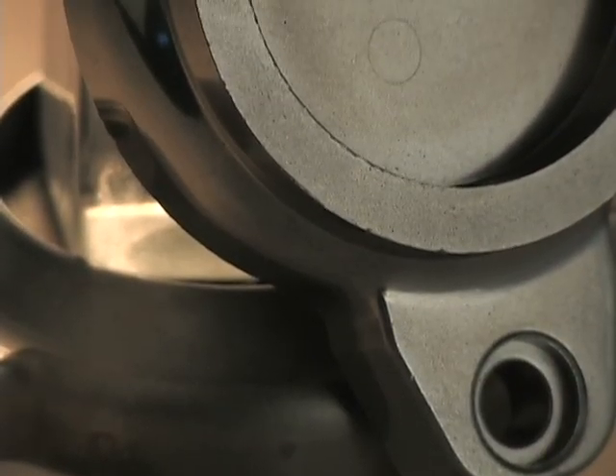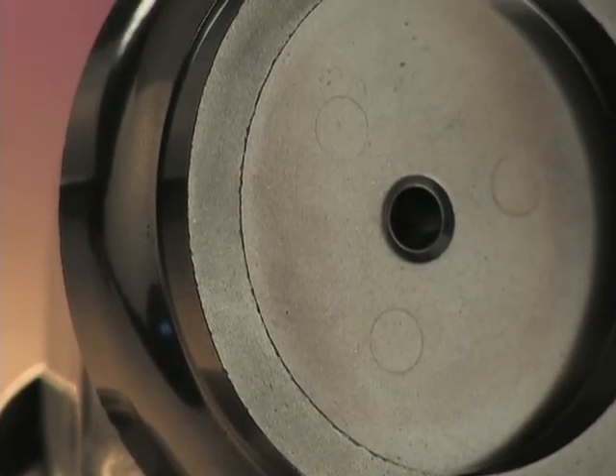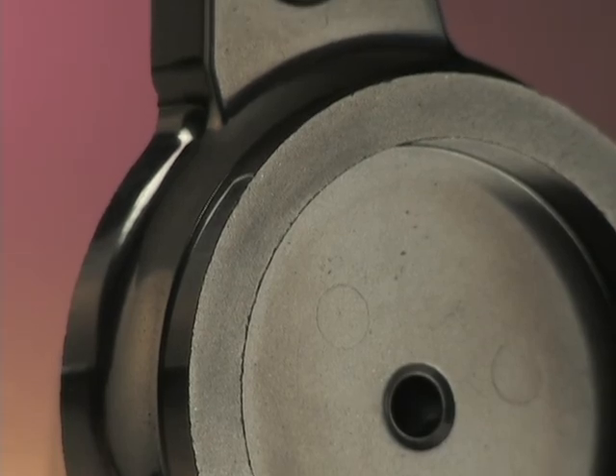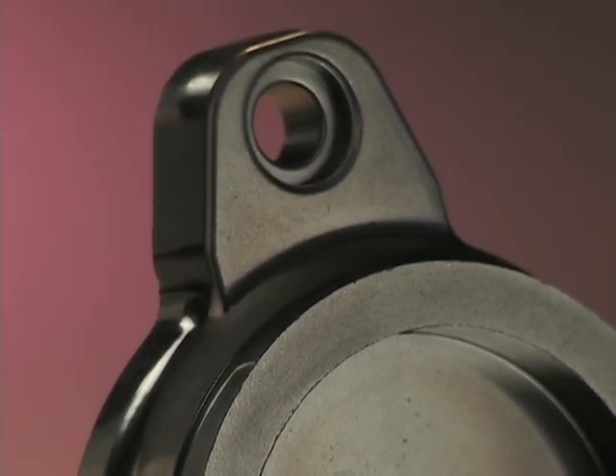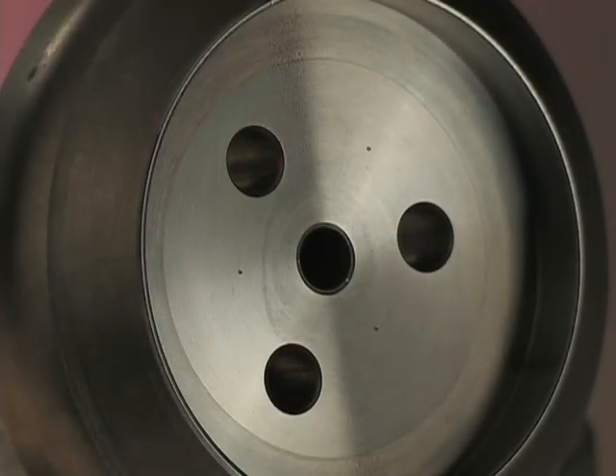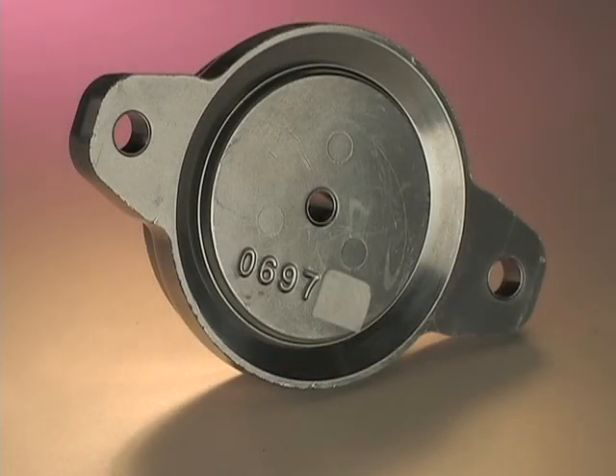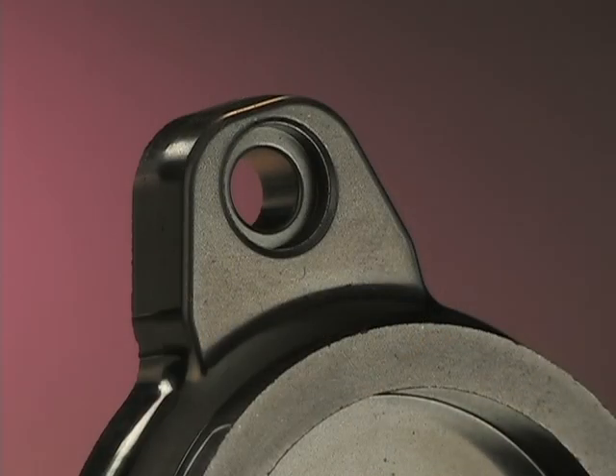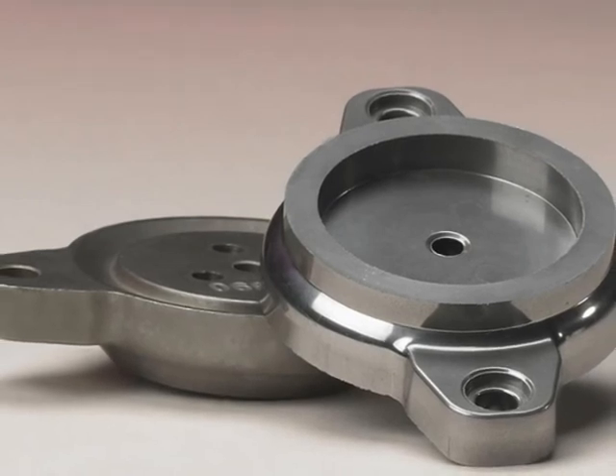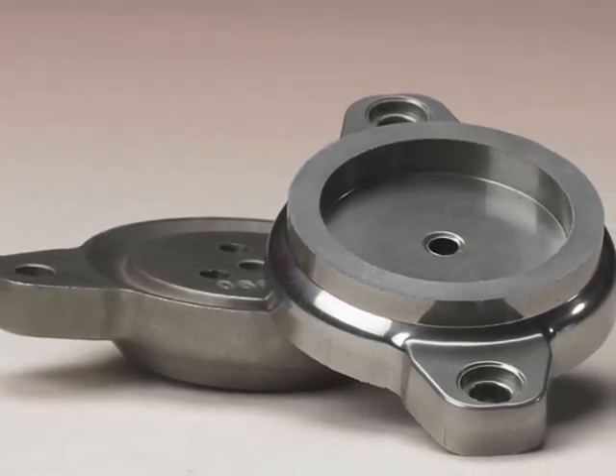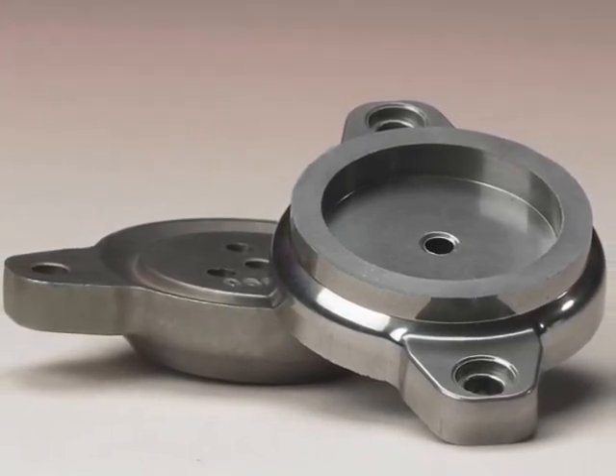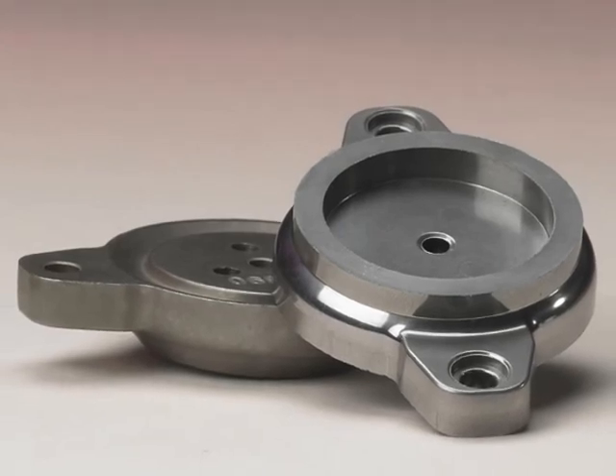The part's outside diameter is designed with a smooth flowing radius to permit gas flow around it with minimal turbulence. Secondary operations include soft machining of 3 gas holes in the counter bore, carburizing, quenching, tempering, and hard turning to form the counter bore diameter and face. Choosing the PM process offered a 30 to 50% cost savings over competing fabricating processes such as casting or stamping.